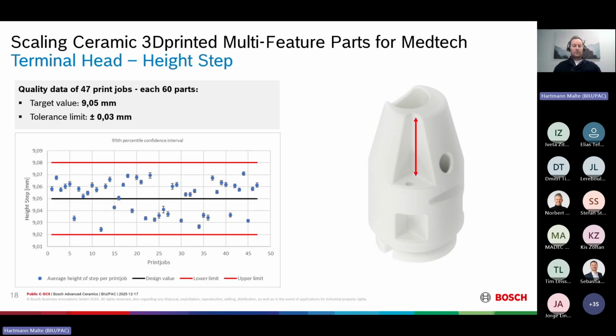If we look at another feature of this part, the target value was 9.05 millimeters and the tolerance requirement was the same. And the Z feature varies just a few microns within one print job. So there's more variation from one print job to another. Some are actually close to the tolerance limits. The reasons here are obviously shrinkage during sintering, different vats that were used during the production, and variation from one printer to another. So here the confidence interval is 2 micrometers and the standard deviation is 7 micrometers.